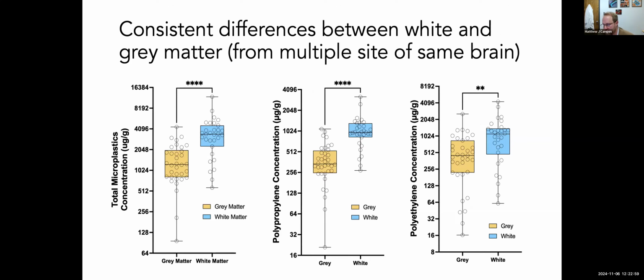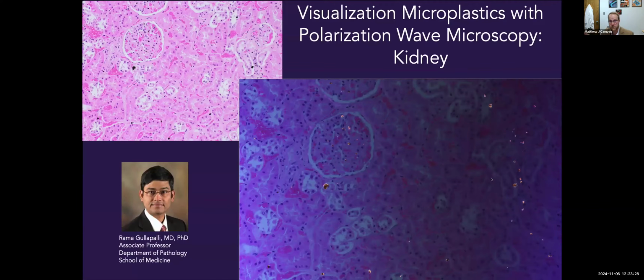The other observation that's been interesting is we're doing this now with a single brain, and we're looking at multiple sites throughout the brain. And what we've shown so far is that there tends to be greater accumulation of these different polymers in the white matter compared to the gray. So you can see total plastics, you can see polypropylene only, you can see polyethylene represented here. All of these are showing a significant difference in their distribution throughout the brain. Okay, so that's mass spec.